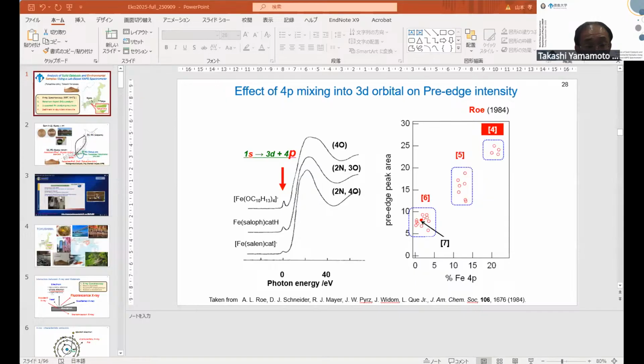So the K-edge XANES spectrum of a 3d element is very sensitive to the coordination environment. In the case of octahedral, the pre-edge peak is very small, but in tetrahedral, a large peak exists. By checking the pre-edge peaks, we can know the coordination environment.